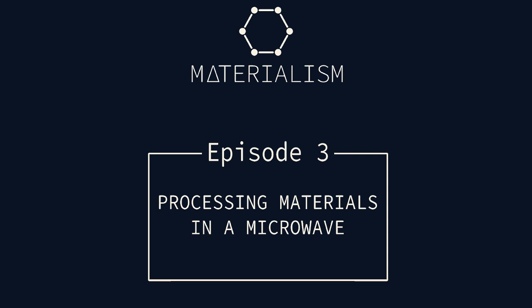Thanks, Andrew. Okay, so microstructure is important, and it's influenced by local temperature within the sample. Now, when materials are sintered in a conventional furnace, they're heated via heating elements, which are sort of surrounding the sample. And what this tends to do is it heats the sample up first along the surface and then eventually within the bulk of the material.